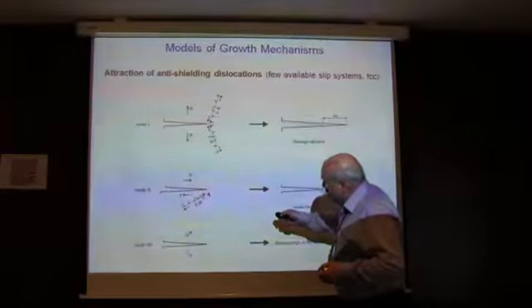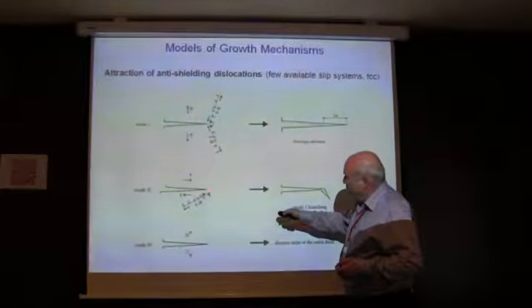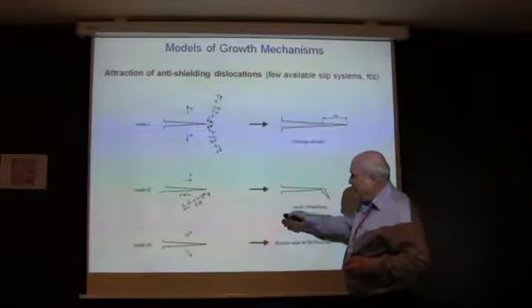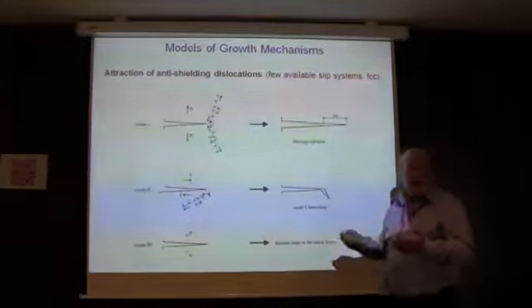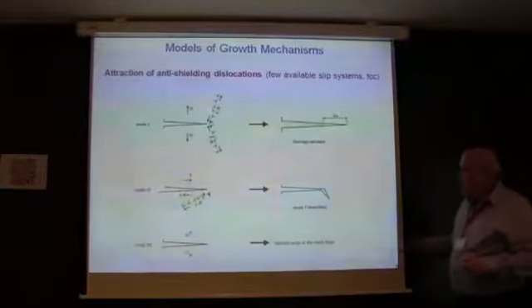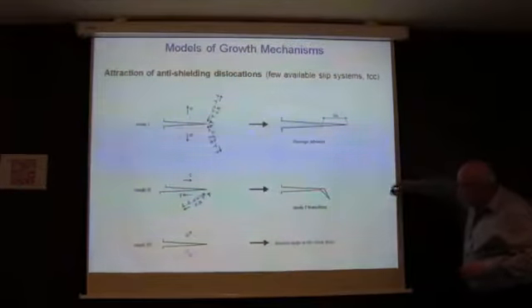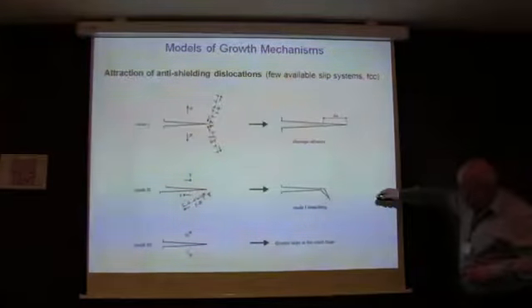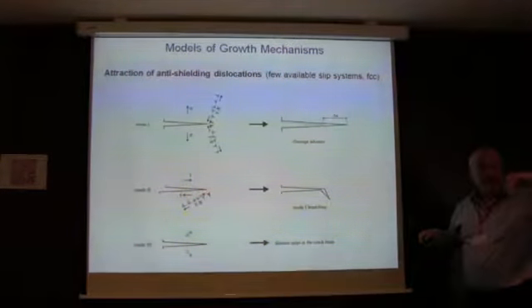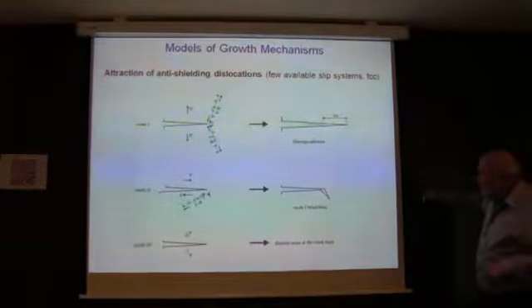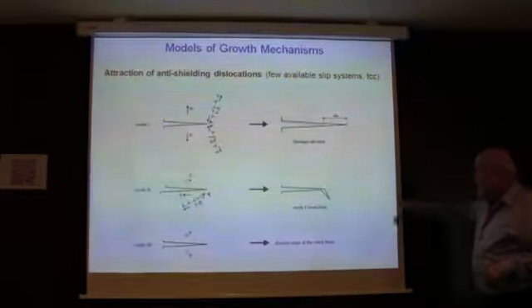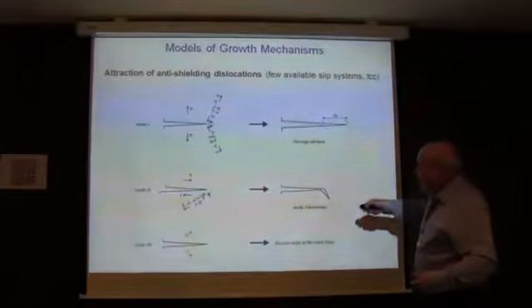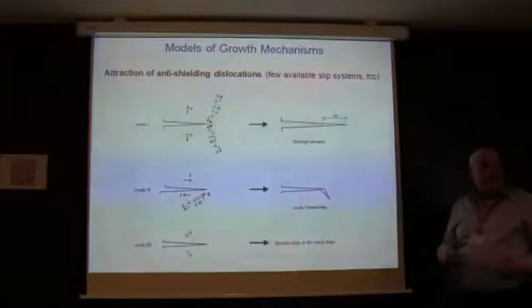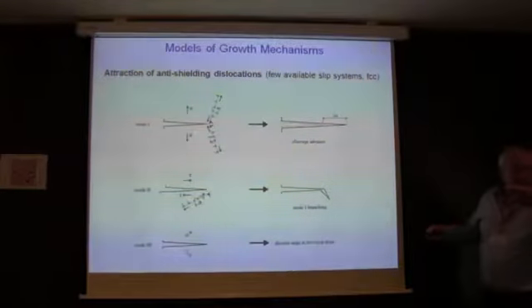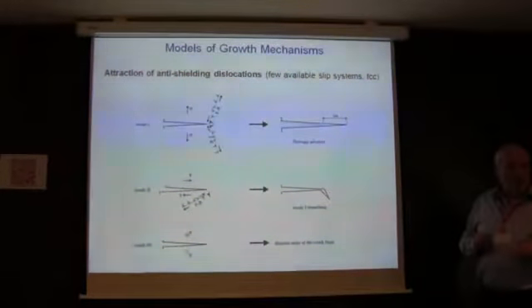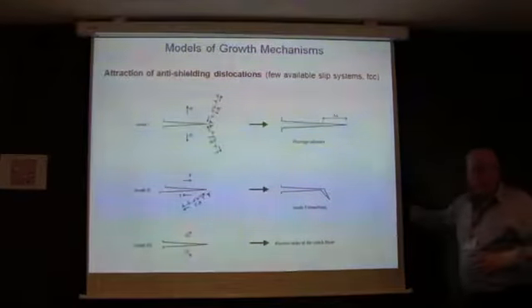But the problem is that if you would like to superimpose the external and internal crack field, you just don't have any superposition of normal stresses. But if the crack would propagate like this, that's a branching, mode 1 branching. So in that case, it immediately becomes a support of external mode 1, and you can have a superposition. So this model predicts a branching of the crack in mode 2.